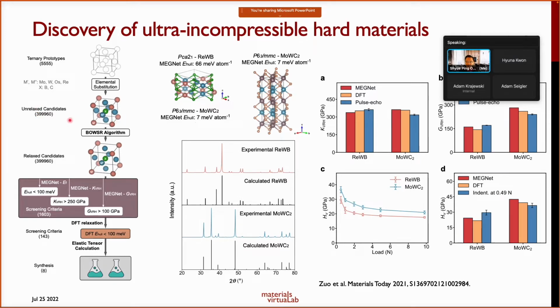And what you will note, first of all, 400,000 is way too many structures for you to do DFT on. Okay, it will take you forever. What we then did was to just use the BOWSR algorithm to relax all the candidates, and we use machine learning models to predict things like the formation energy, bulk modulus and shear modulus, and then we screen all these materials using these criteria.